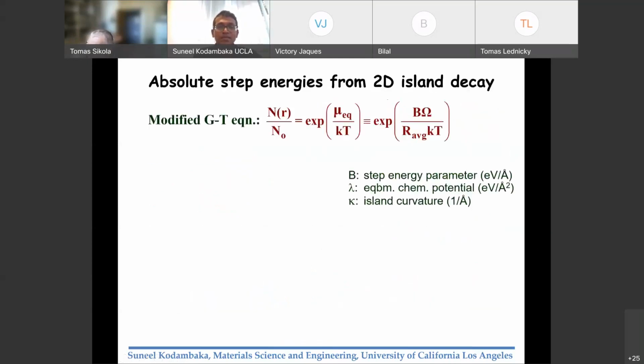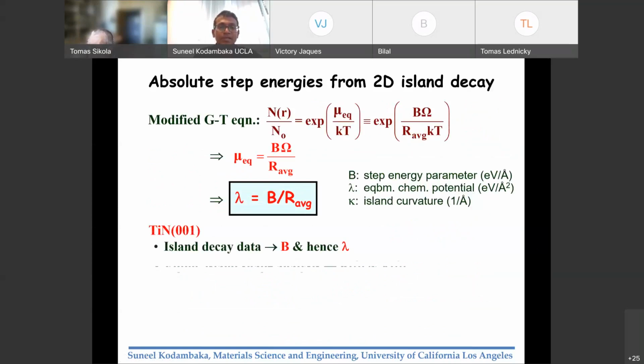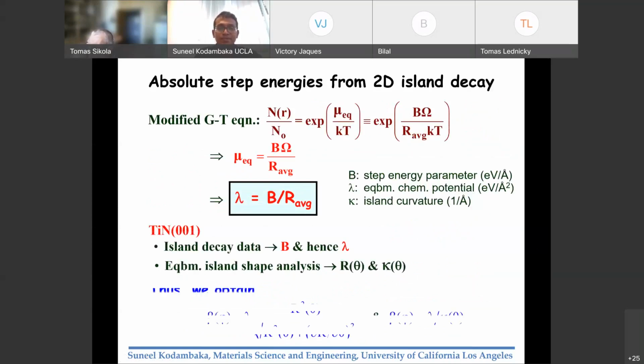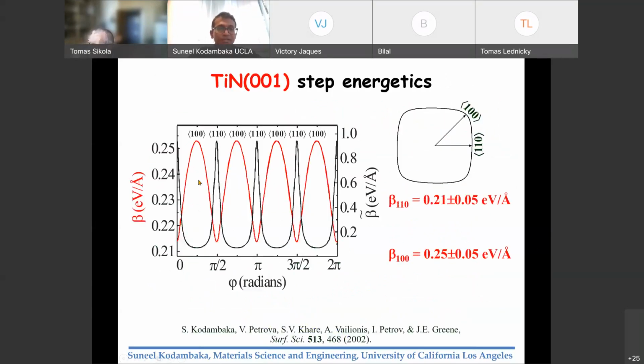And so we can now obtain the chemical potential of each of the islands. And once we have it, we get the absolute step energies, and here is the data. So the beta, the red curve, shows the actual change in the step formation energies for titanium nitride steps as a function of step orientation. Okay. And the step stiffness also one can calculate once you have step formation energies, and that follows as shown by this black curve.